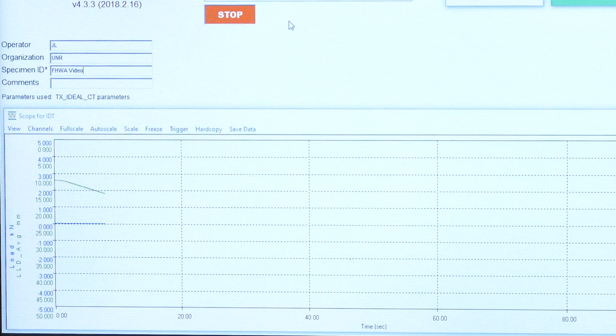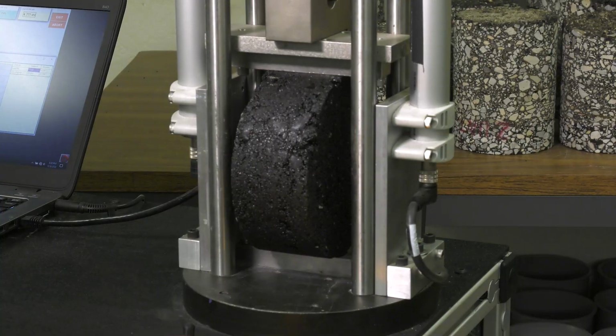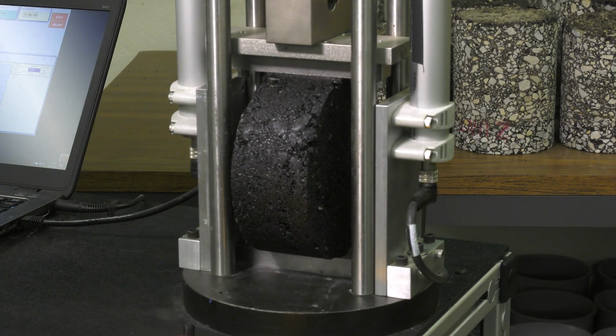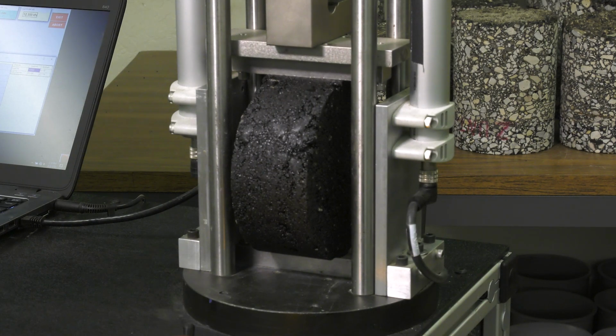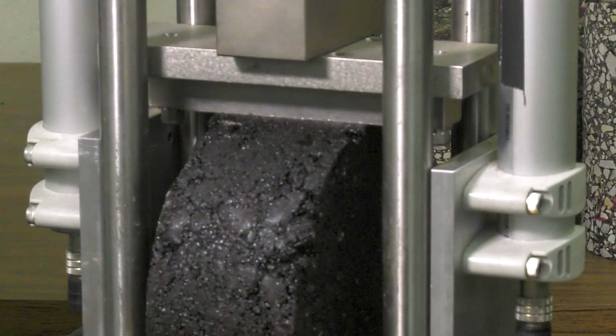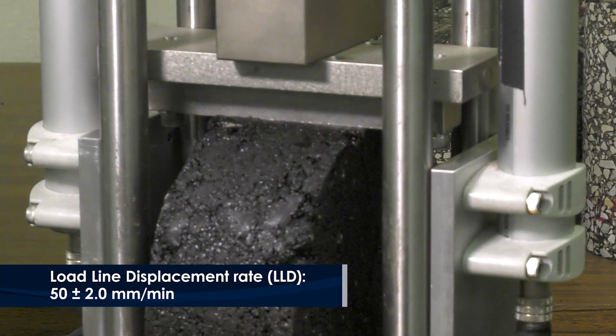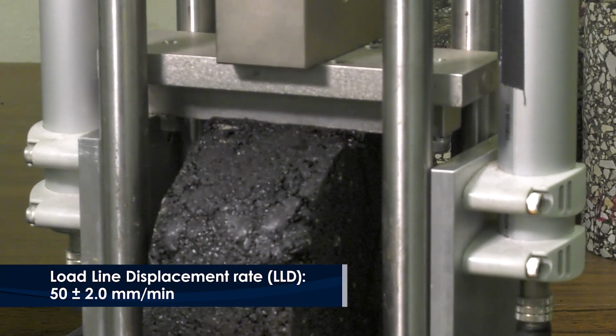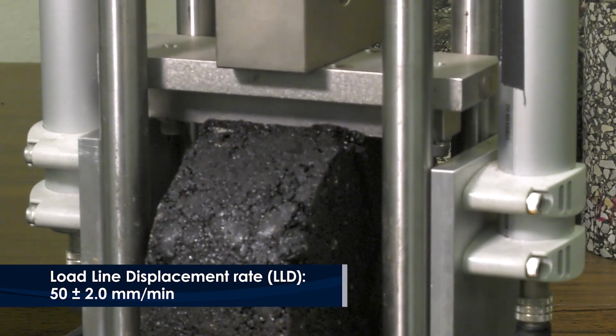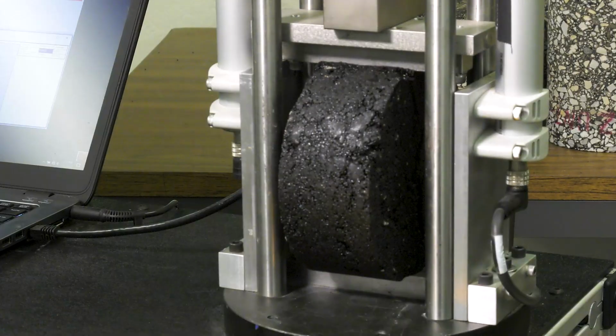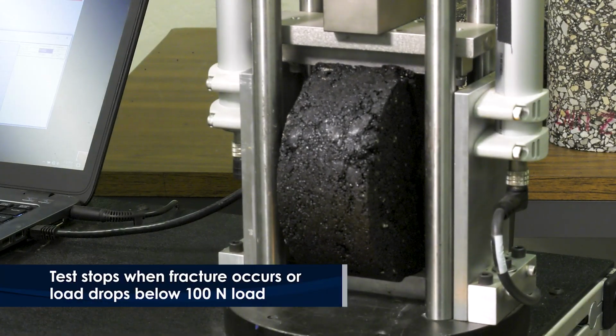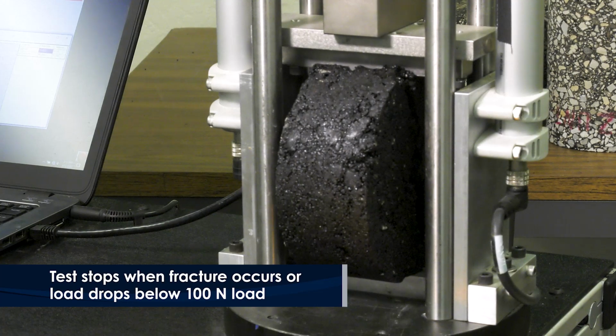The test should be completed within 4 minutes of removing the specimen from the environmental chamber in order to maintain the specimen's specified test temperature. Apply load to the specimen in load line displacement, or LLD control, at a constant rate of 50 mm per minute. Stop the test when fracture failure occurs or the load drops below 100 newtons.